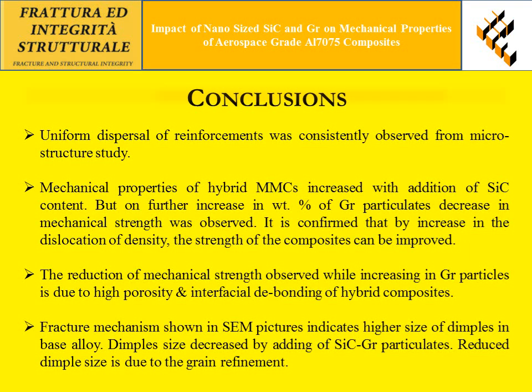The reduction of mechanical strength observed while increasing the graphite particulates is due to high porosity and interfacial debonding of hybrid Metal Matrix composites. Fracture mechanisms shown in the SEM pictures indicate higher size of dimples in the base alloy, and dimple size decreased by adding silicon carbide and graphite particulates. Reduced dimple size is due to the grain refinement.